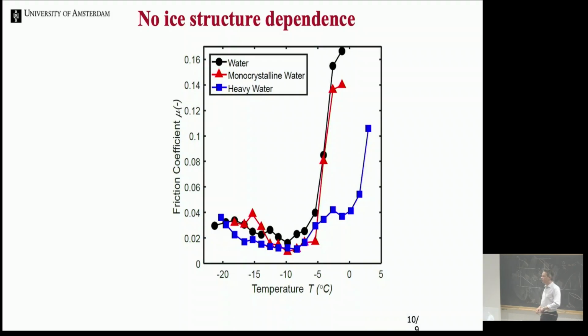And so this doesn't really depend on the way we make the ice, because that was also a large discussion in the literature. I can make polycrystalline ice because that's very easy. My brother can make monocrystalline ice because that's very complicated, but if we do the experiment, they give the exact same results. And we can also make ice from heavy water, and that gives something very similar, only the melting point of heavy water is slightly higher than 0 degrees. Yeah, so this is a robust result, yes.